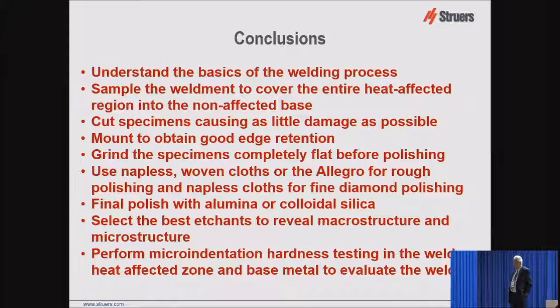polishing steps with diamond. Now, final polishing, you're going to either use alumina or colloidal silica. They're the two most common, depending on what the alloy is and so forth. But you want to use a cloth that you can control the flatness with and the proper load on the sample against the cloth. And you want to select the best etch to reveal macrostructure or microstructure. If you're going to do micro-indentation hardness testing in the weld, heat affected zone, base metal, that's a great technique to understand what's going on in addition to looking at the microstructure.